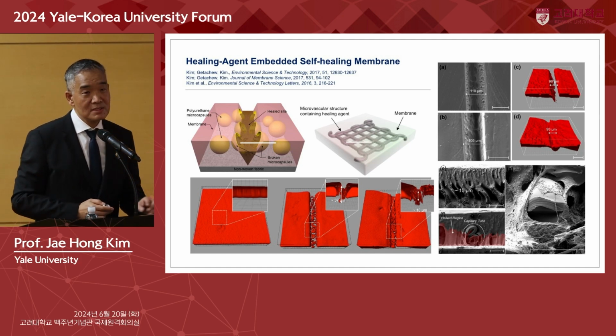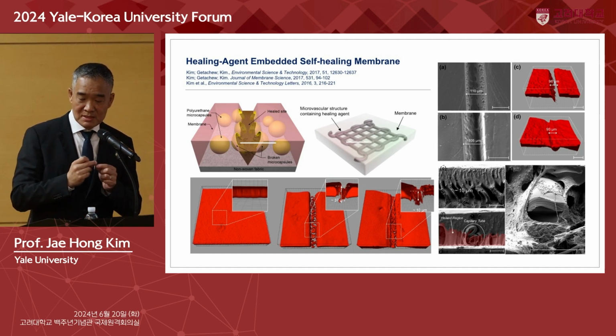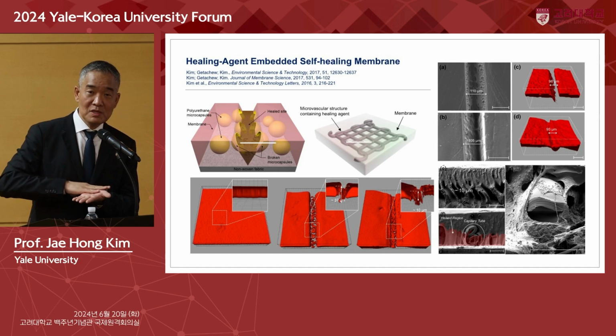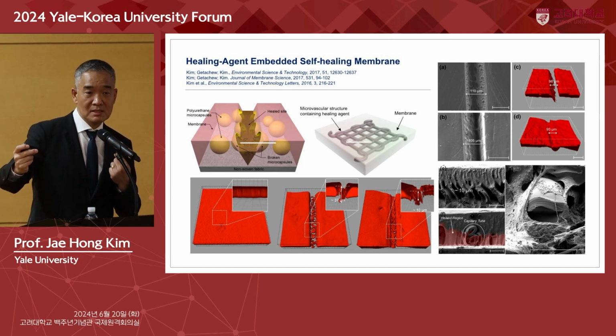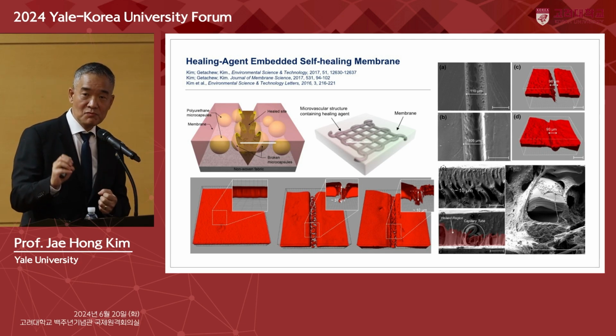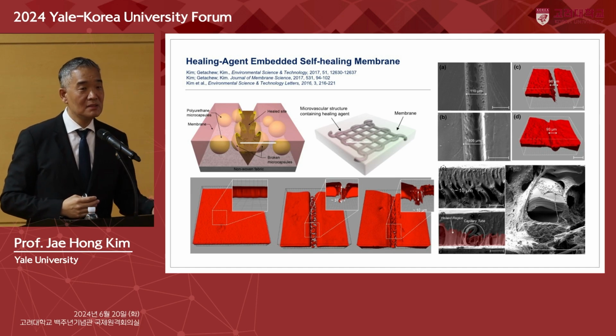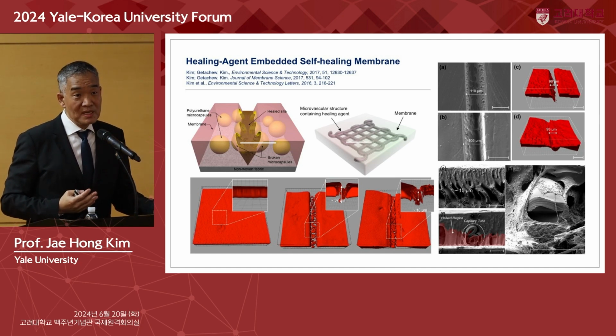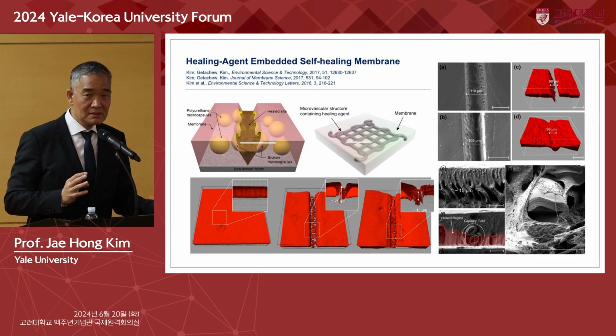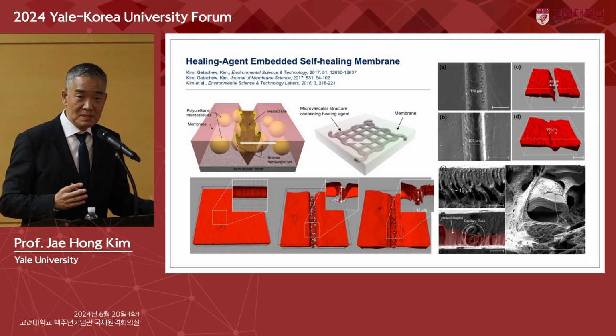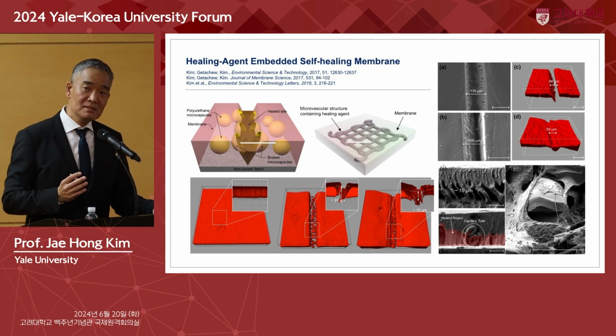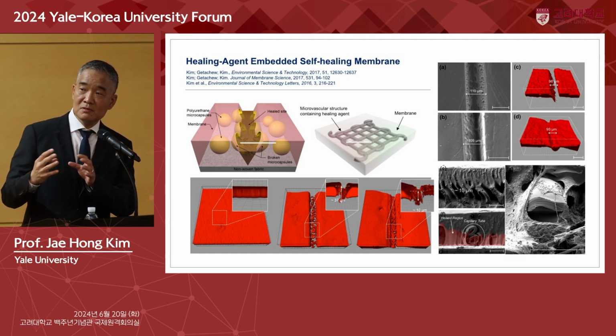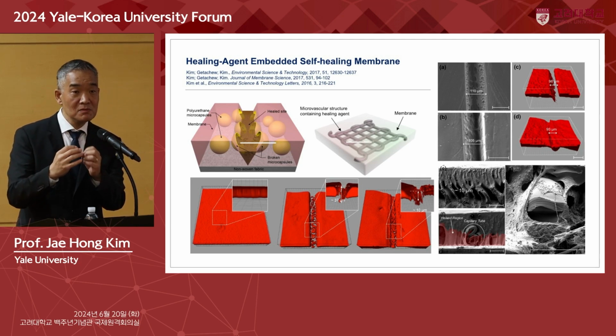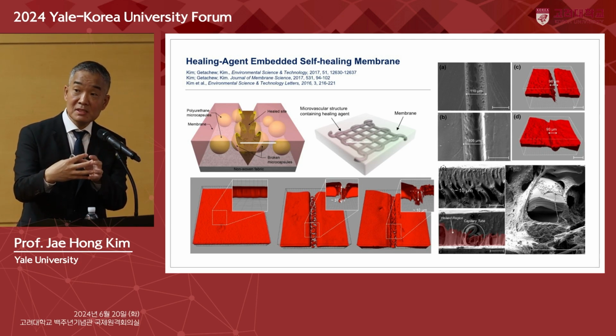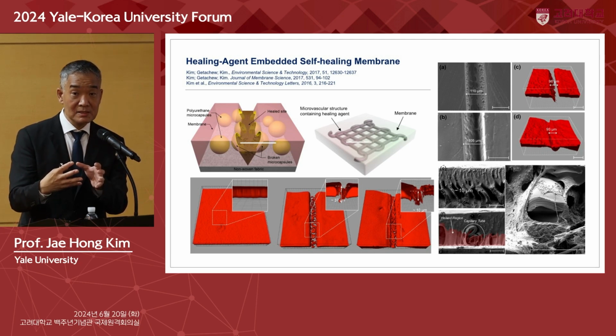Our second generation used a microvascular network, basically a tube. We have a network, and then we grow the membrane on top so that the tubes provide physical strength, but at the same time, when they get broken, they release the glue and fix it. Again, the synthesis was painful. It worked well, but we were unhappy about how it was functioning. On top of that, when you use this kind of super glue, and there's a damaged site, it releases the glue and fixes it, but that area becomes completely blocked. That is the first dilemma that we had, right? It doesn't work.